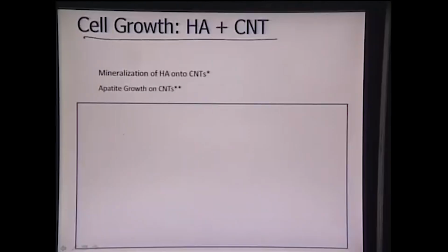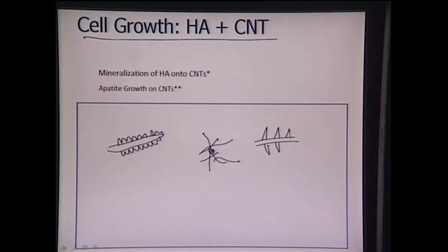So what we are seeing in this particular hydroxyapatite plus CNT is that all the CNTs are showing some precipitation of apatite mineral onto them. So there is some sort of barbed wire-like structure, like what we use in fences. We see all the fences have wires grown all around them. Similarly, we are seeing that CNTs have some sort of needle-shaped structure being grown over them, so they become more like a barbed wire structure which is appearing onto the CNT surface.